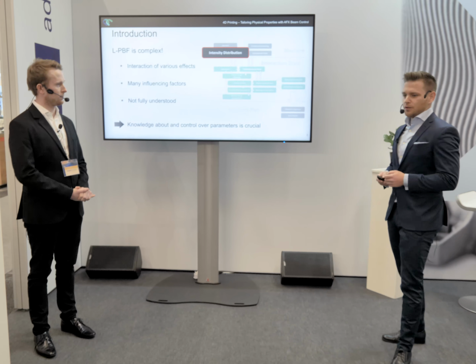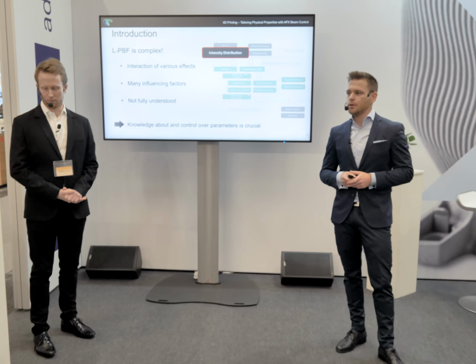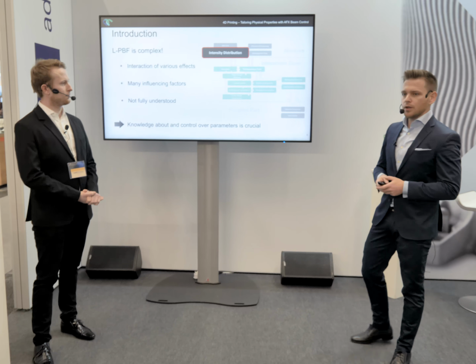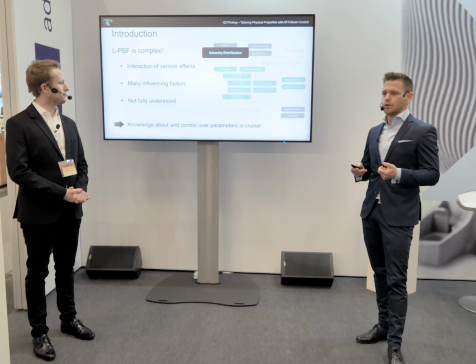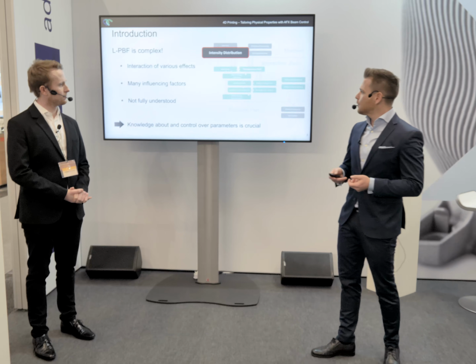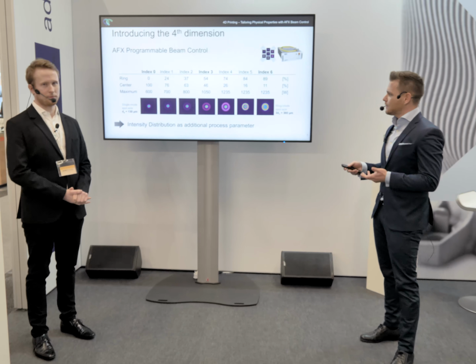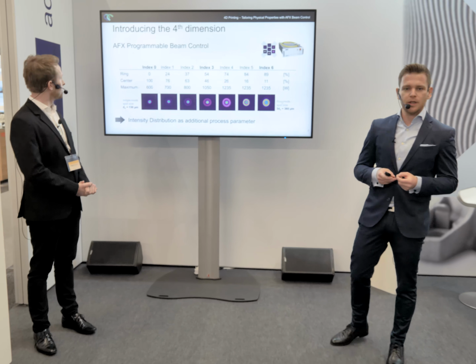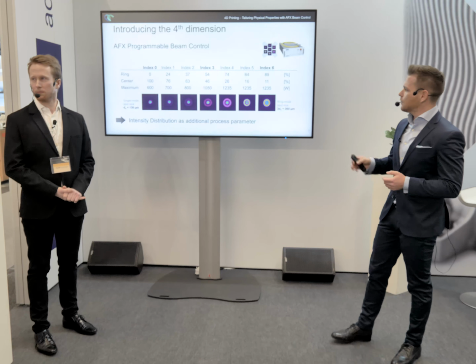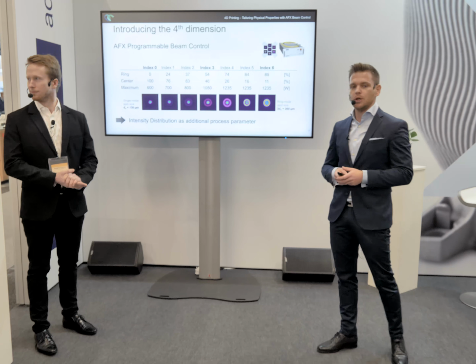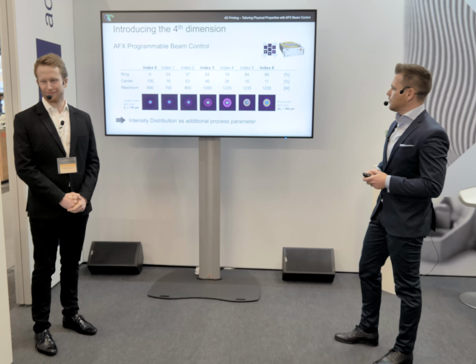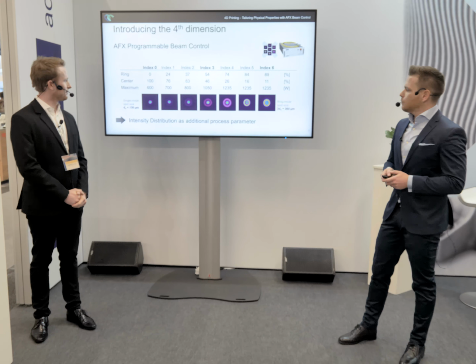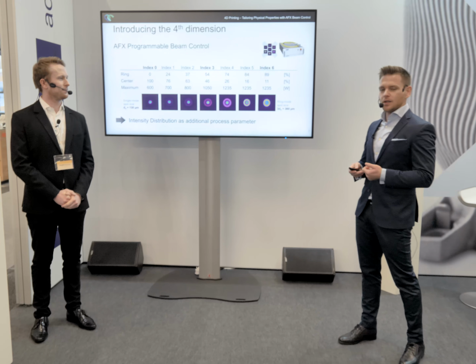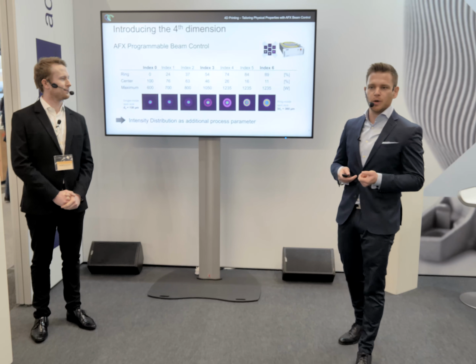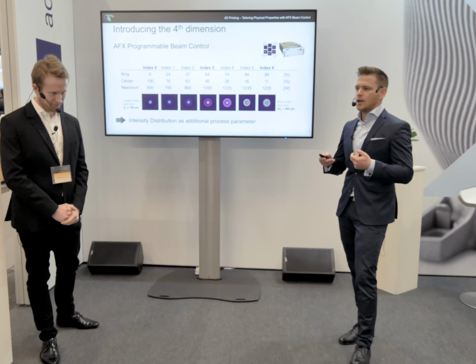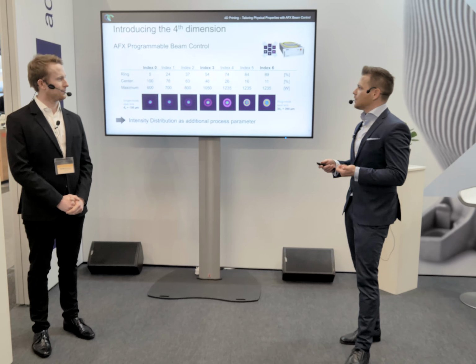One main influencing factor here is the intensity distribution of the laser. And while common lasers operating with a standard Gaussian beam need to be complemented with complex setups, the nLIGHT AFX is able to set 7 different intensity distributions within the process in 30 milliseconds. And doing so, we have index 0 as the standard Gaussian beam, index 6 as a ring profile, and 5 indices in between. So we are going to have intensity distribution as an additional process parameter, and this is our fourth dimension in handling these different intensity distributions.